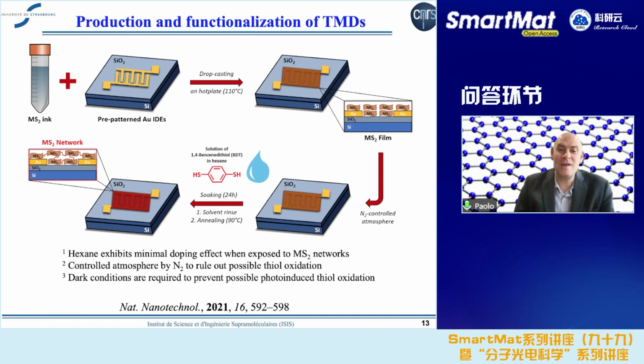Okay, so let's say azobenzene is, of course, more established. Among photochromic molecules, the one for which you find more papers reported is azobenzene. The problem you have with azobenzene, but this is also a problem of the spiro, is that the second state, which can be the cis or the mero, is not thermodynamically stable. So that is not good for electronics applications, because after a while it goes back thermally